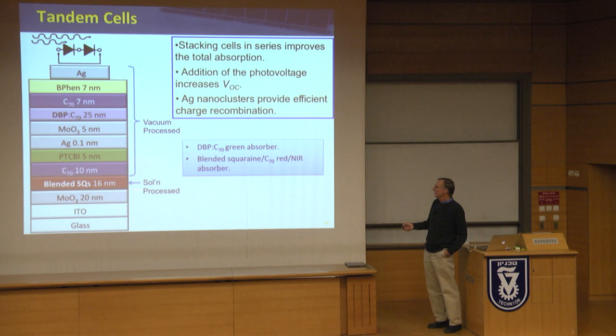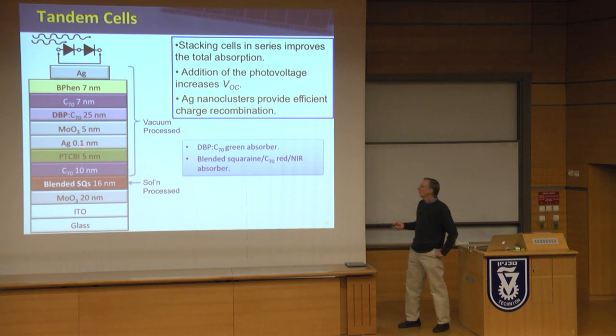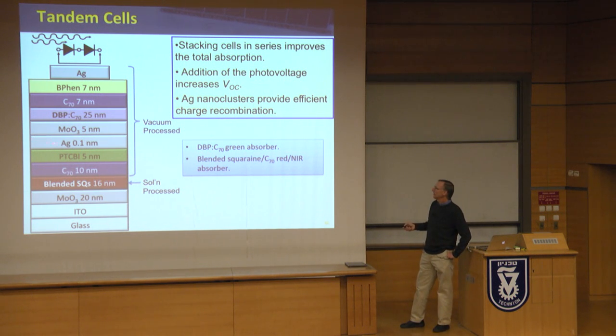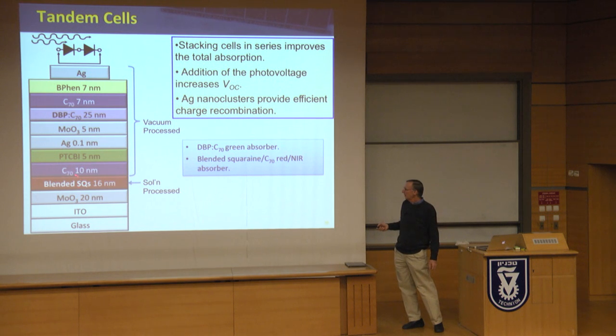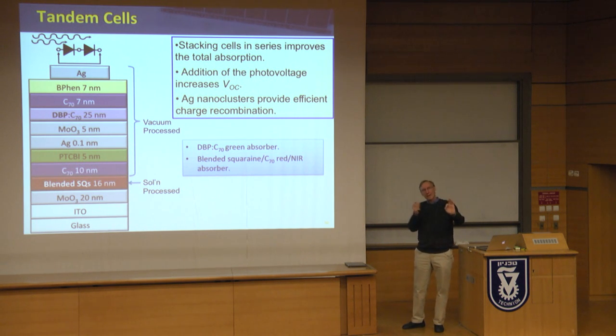We put down a solution process blended squaraine, which is a bit different than that other donor. C70 here. We need to have a charge recombination layer down here, and for this we use about 1 angstrom of silver. It makes little nanodots or nanoparticles, so that when an electron drifts up from this side, when it sees the sphere, it sees its image, and it gets attracted to that image.